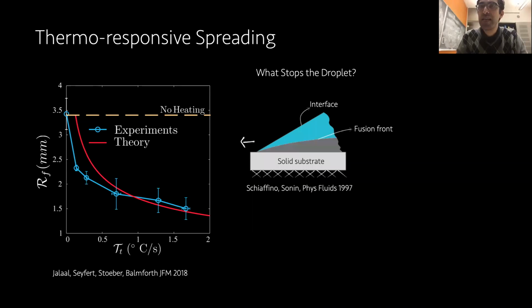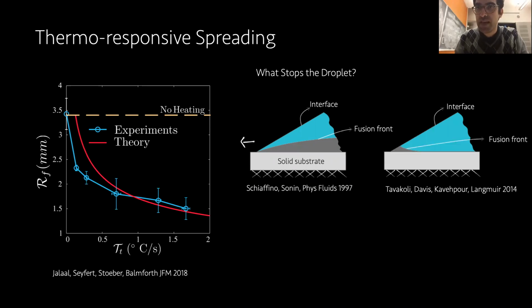And we also, as I said, there was this long-standing question of what stops a spreading droplet that is solidifying on the surface too. There were two dominant theories in the literature. One of Sonin at MIT, who assumed that air is fully insulating, therefore the fusion front looks like this. There was a counter theory of a group of Pirouz Kavehpour at UCLA that says no, actually because of air you get a solidification front that looks like this, and that will stop the droplet.